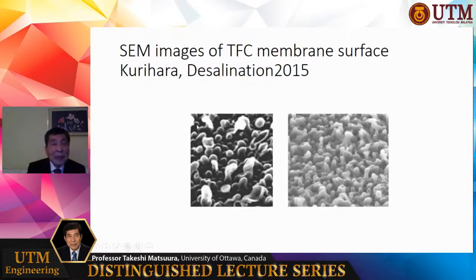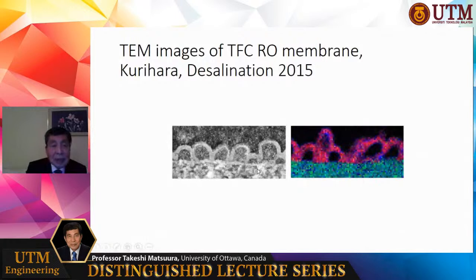So we look at the surface of this TFC membrane. It is not smooth at all. This is a SEM picture. It is not smooth at all. It is very rough, and each unit is called a nodule. There are a number of nodules on the surface. And when you look inside the nodule, this is a TEM image, you can see the void inside the nodule, and it is covered by a very thin layer of polyamide.